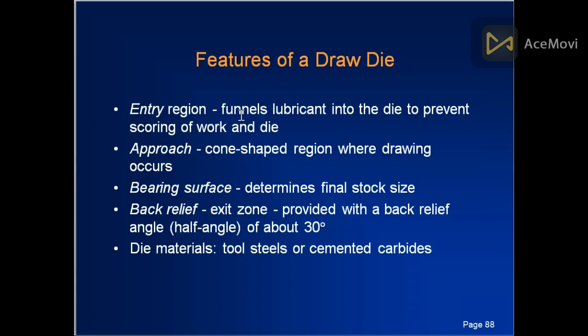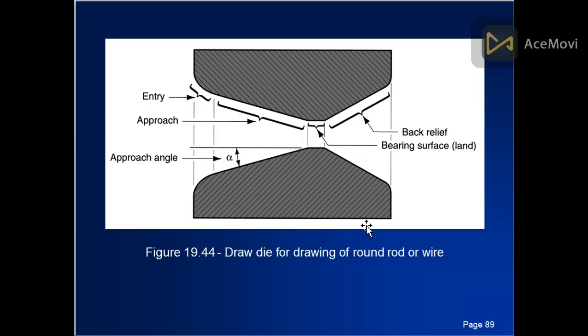Features of the draw die: the entry region funnels lubricant into the die to prevent friction. The approach is the cone-shaped region where drawing occurs. The bearing surface determines the final stock size. Back relief is an angle, with a back relief half angle of about 30 degrees. Die materials are tool steels or cemented carbides. This is the entry region. This is the approach, this is the bearing surface, and this is the back relief. And this is actually the approach angle.